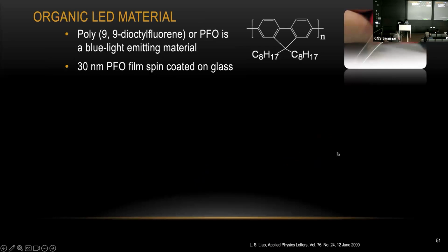Finally, it comes to almost my last slide here. This is just a case study for some organic LED material. It's a PFO, a very strong blue light emitting material. And the coating is about 30 nanometer, a thin film, spin coated on glass. And we need to determine the electronic property for this coating.